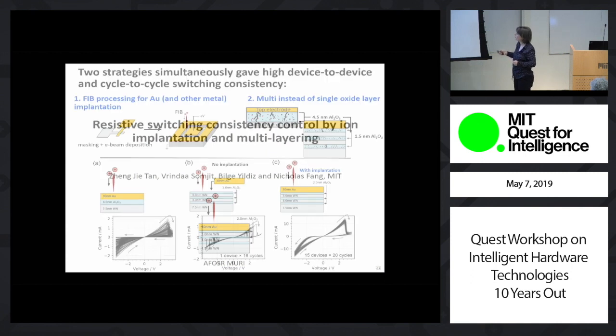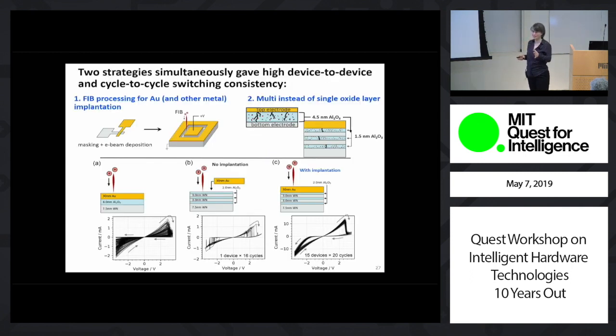Okay? And the point will be that you need to do two things apparently in this system. So if you are working with alumina as the switching layer, electrolyte, two strategies simultaneously when you implement them give rise to very good consistency. First is that you must be FIB milling after you put the metal contact on top, and you must divide this single alumina layer into 2 or 3 or more layers separated by the conducting layers in between. So if you do the two of them together, apparently you get really good consistency.